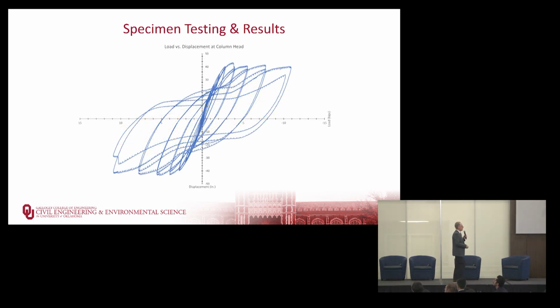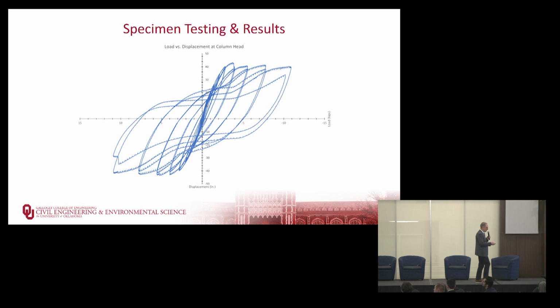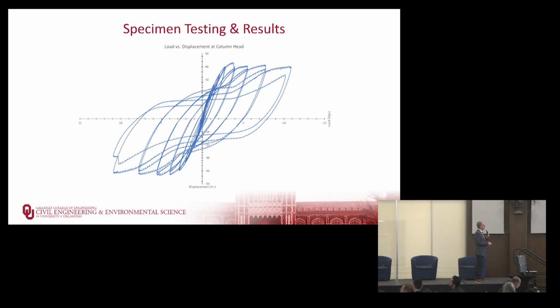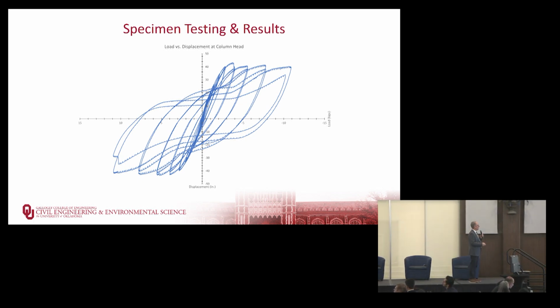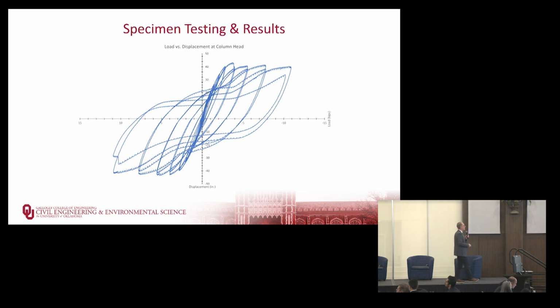So this is for the column with the high strength SCC core. Again, you can see a nice linear elastic response in the beginning, and then eventually the concrete starts to become nonlinear in compression, right? Concrete becomes nonlinear at about 40% of its compressive strength. You start to yield the outside edges of the steel tube. The steel tube is the only thing embedded into the footing, right? The FRP tube stops at the top of the footing. It provides no longitudinal resistance. It mostly provides confinement for the concrete core, increasing its apparent strength and acting as formwork.